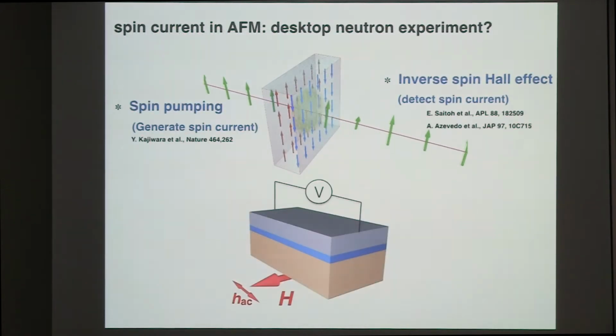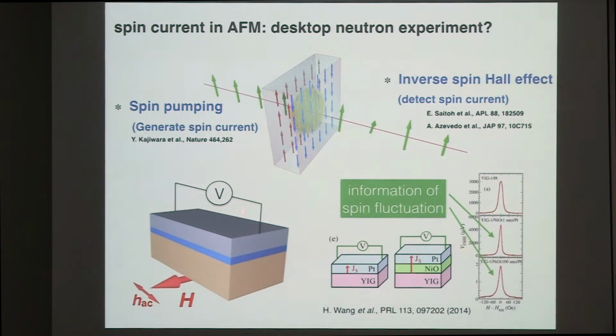If we look closely, we find that this kind of spin injection is very easily realized by spin pumping as the spin source and the inverse spin Hall effect as the spin detector. And we just mimic the others, making these trilayer samples, which look like this. Now we still look at the same data, but because we have a subjective guess, we believe that some fluctuation of spin is already included in this signal.